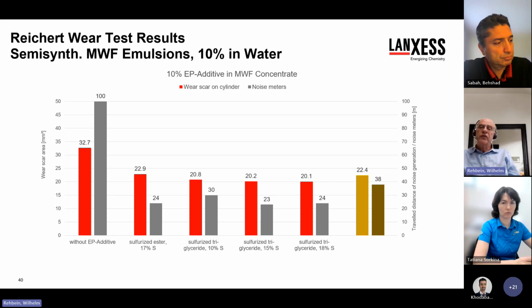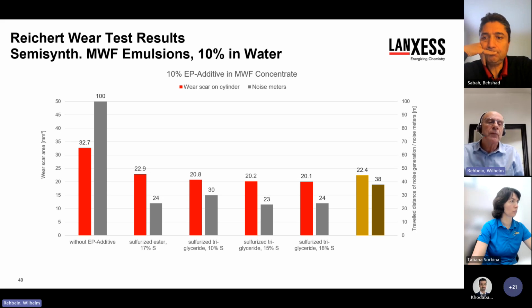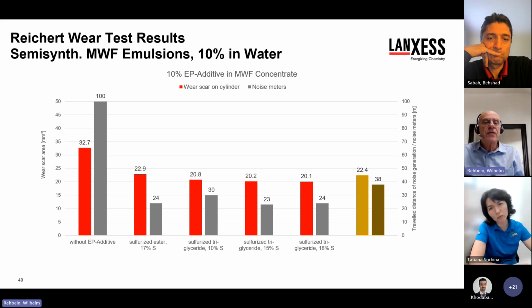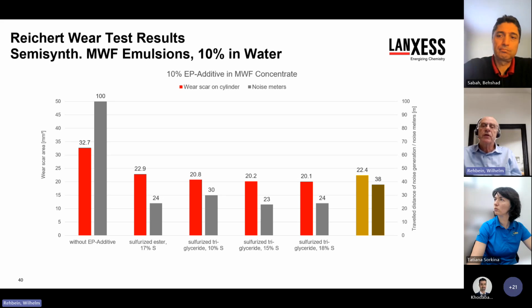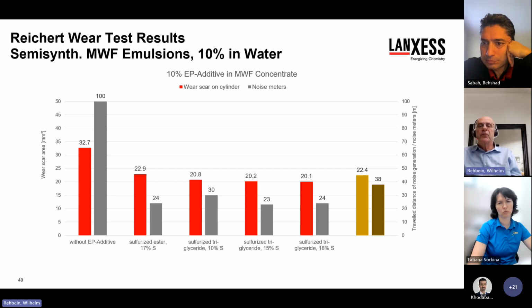And with increasing sulfur content and activity, the duration of the noise generation becomes shorter. You can see this if you compare the sulfurized triglyceride with 10% sulfur content with the other triglycerides containing 15 or 18% sulfur. So this is a clear indication for faster formation of the protective EP layer. And compared to a long-chain chlorinated paraffin that we tested as well, the performance of the sulfurized triglycerides, the active ones, is significantly better.